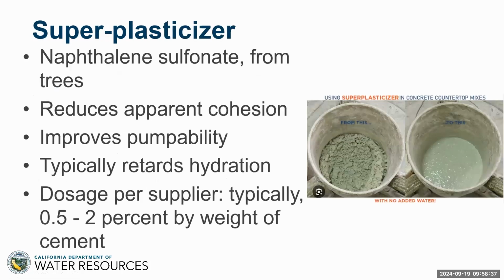Okay, next one. So superplasticizer. A typical one that's used throughout the country is a naphthalene sulfonate, which is made from trees. More recently, companies like Master Builders and so on have started using mineral superplasticizers in smaller amounts, very potent. So what does the super P do? Well, it coats each of the cement particles with a negative charge, and that causes them to repel each other, just like magnets. And so that makes them want to move around more. So it helps their mobility. Most super Ps will also retard hydration a little. And if you want to know how much to add, then you just phone Master Builders or Sika or the other suppliers, and they will typically tell you 0.5 to 2% by weight of cement, depending on how much extra fluidity you need.